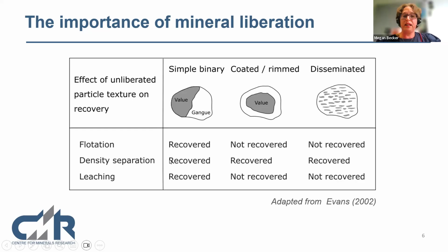If you're going for something like density, then the particle texture doesn't really make a difference. It's about the absolute mass of that particle. Then over here, depending on how the density cut point is set, this is likely to be recovered, that will be recovered, and that texture will be recovered.